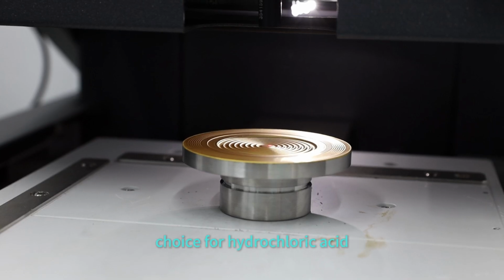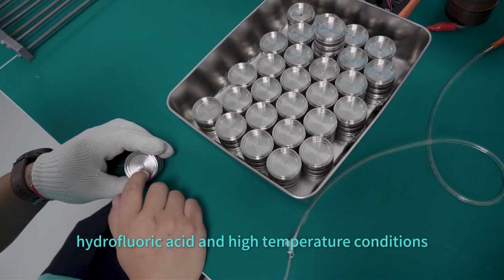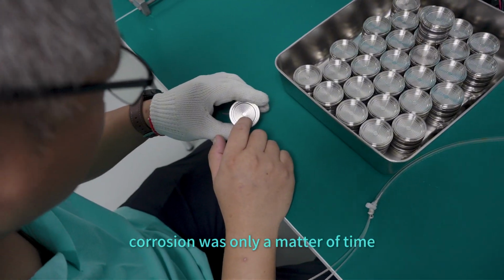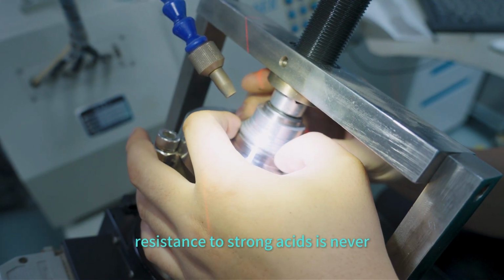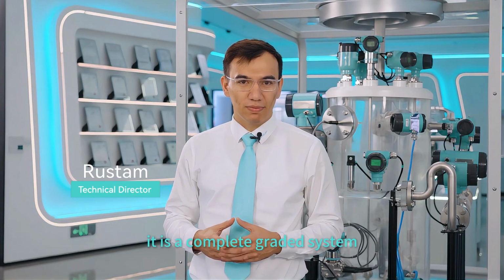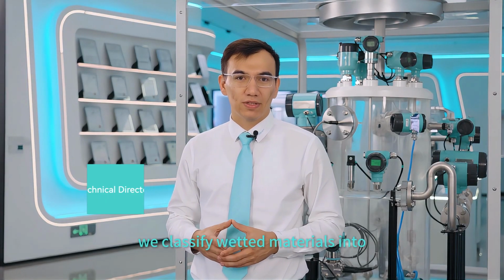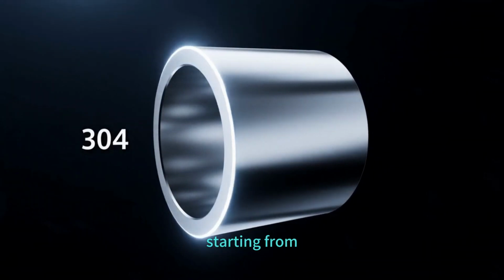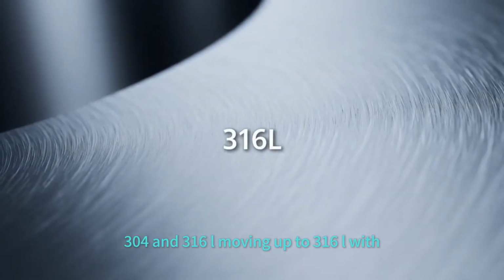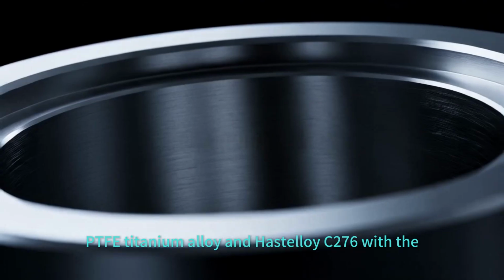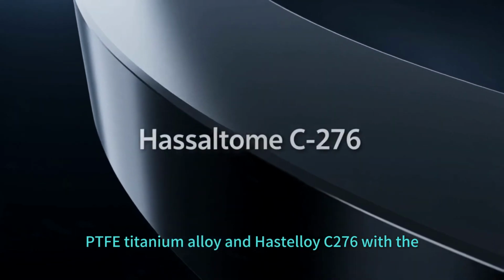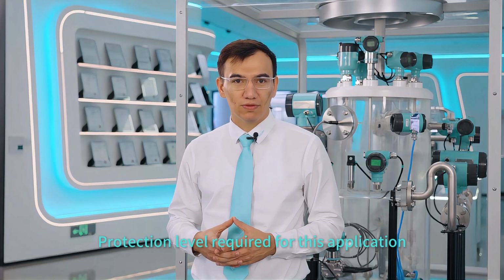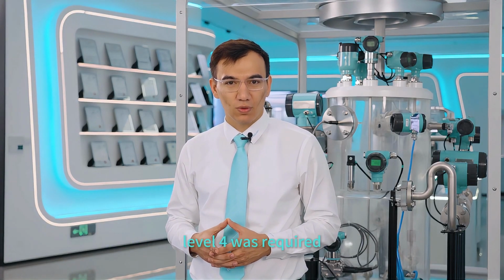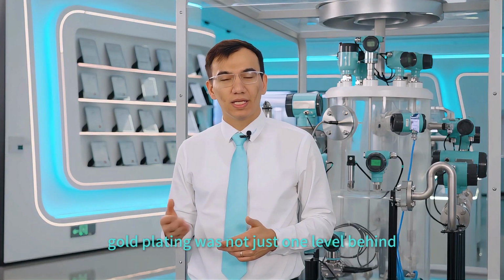Gold plating was never the right choice for hydrochloric acid, hydrofluoric acid, and high temperature conditions. Corrosion was only a matter of time. Resistance to strong acids is never just about changing one material. It is a complete graded system. We classify wetted materials into 5 corrosion resistance levels, starting from 304 and 316L, moving up to 316L with PTFE, titanium alloy, and Hastelloy C-276, with the highest protection level achieved through tantalum diaphragms and full PTFE ceramic solutions. The harsher the operating conditions, the higher the protection level required. For this application, level 4 was required. Gold plating was not just one level behind, it was far from enough.